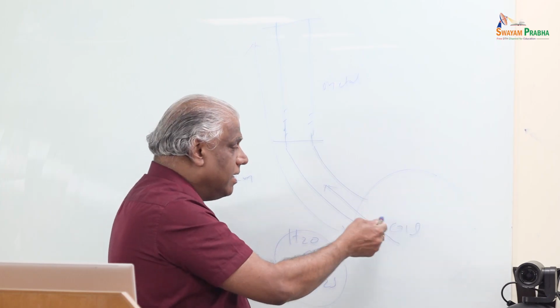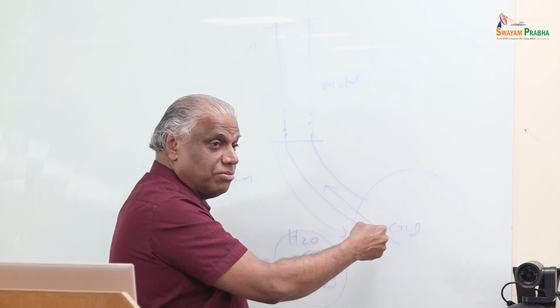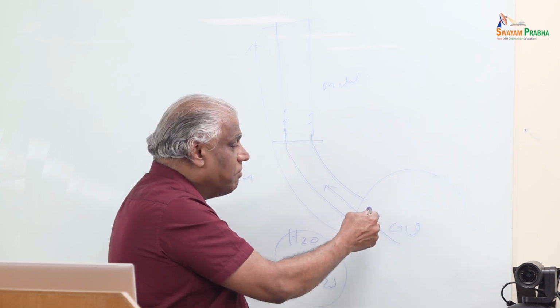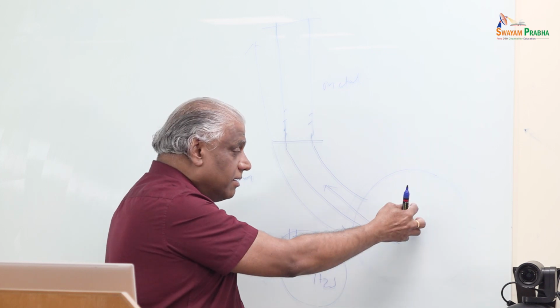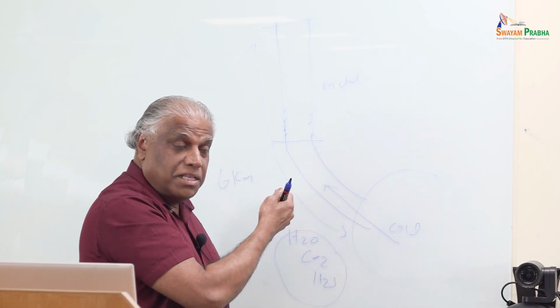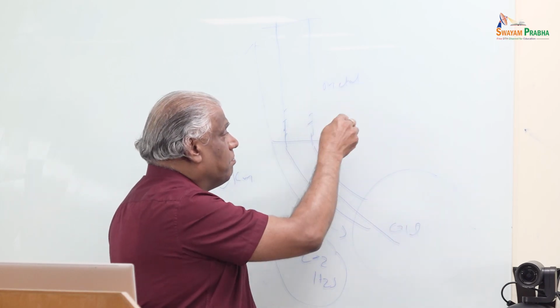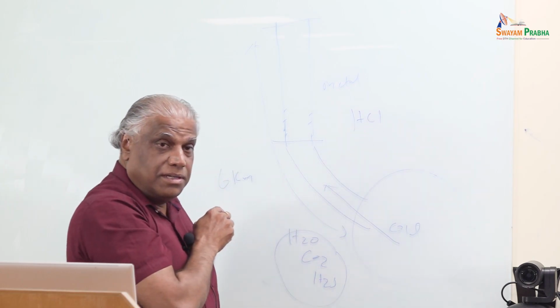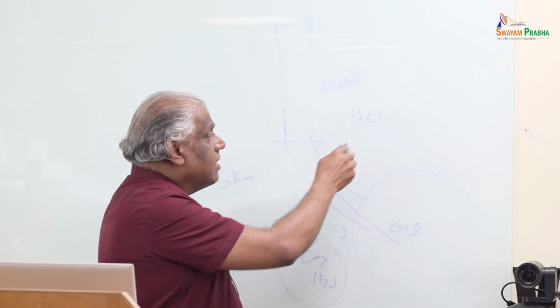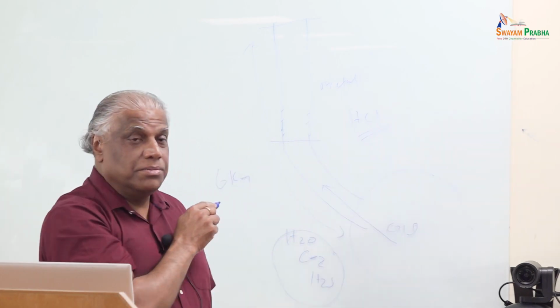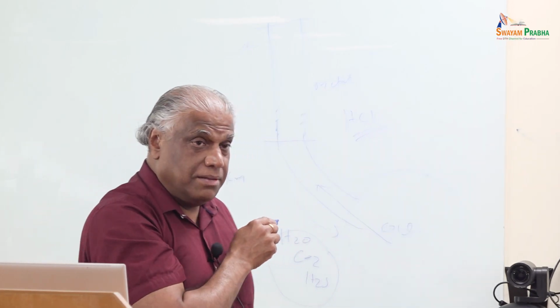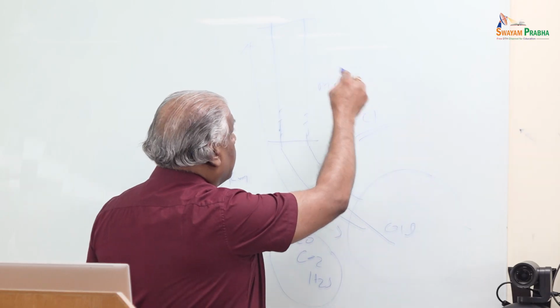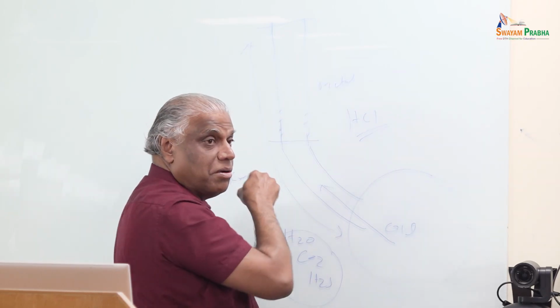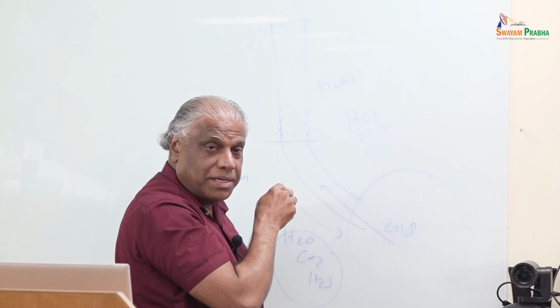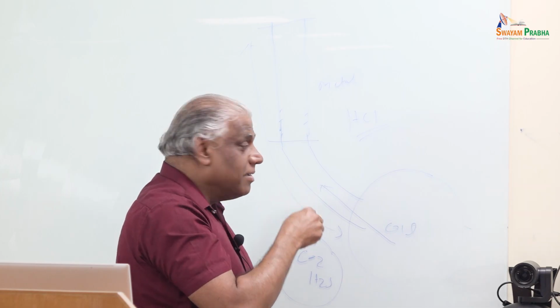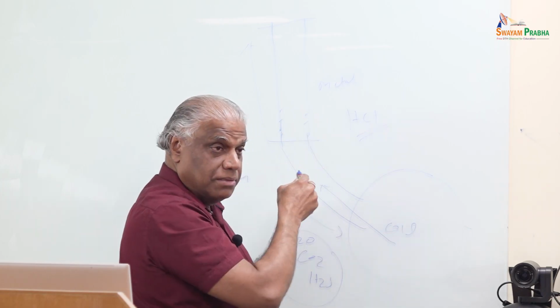So for example, initially the reservoir is very solid, so it has to be fractured so that the oil will come out. This fracturing is done by putting some acid into the well. So this acid they need to deoxygenate. Or sometimes they add the inhibitor into the solution so that the corrosion will not be high. This inhibitor solution has to be deaerated. This is one thing. Second thing is, now the oil is coming out.